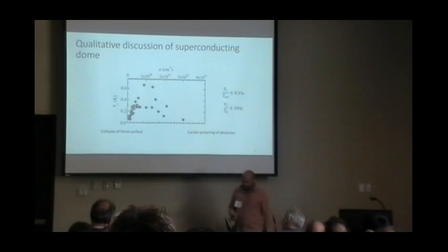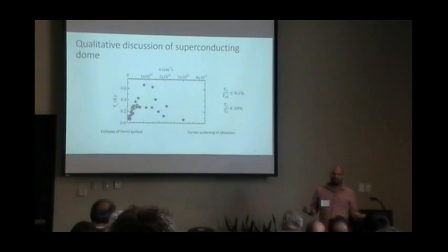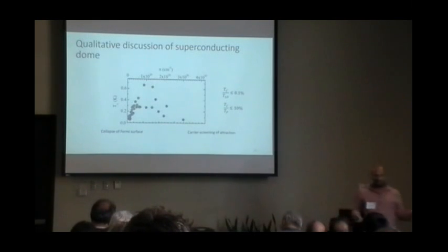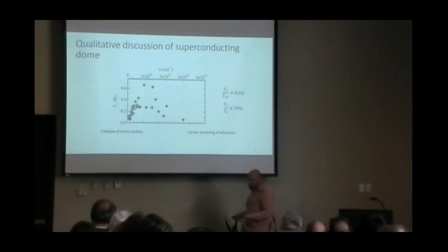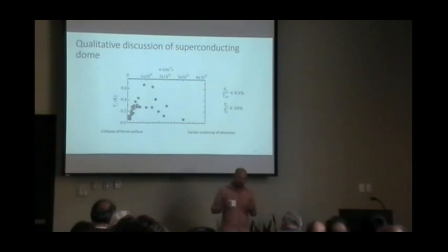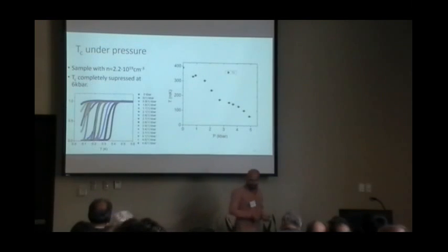possible anymore. So this, of course, is related to the fact that the transverse optical phonon modes get close to 0, close to the quantum critical point, which is at negative pressures. Logically, if this idea is true, when you now apply pressure, you should be able to suppress this interaction with very low pressures. So this is what we have done.